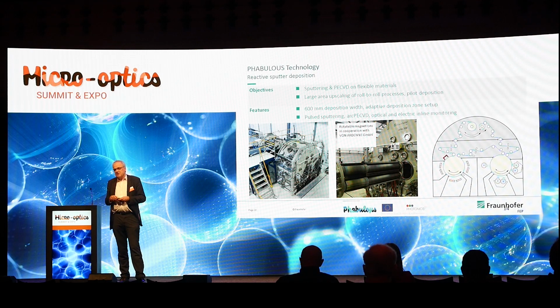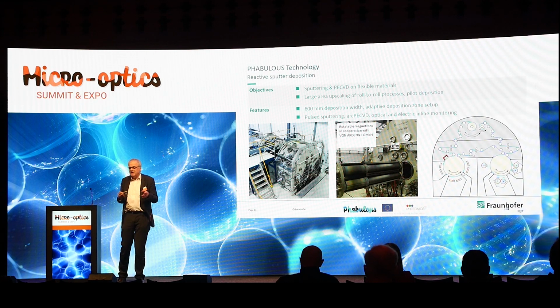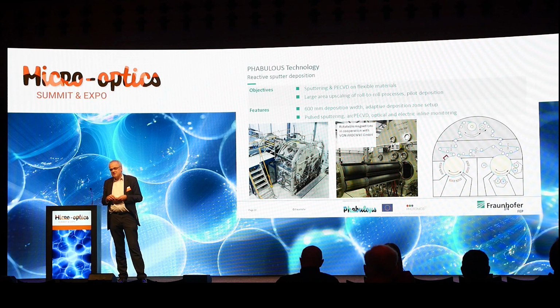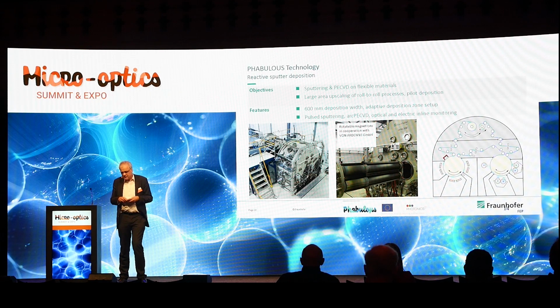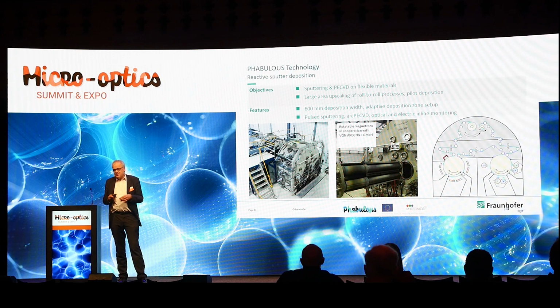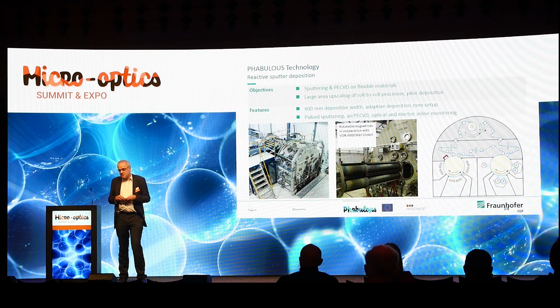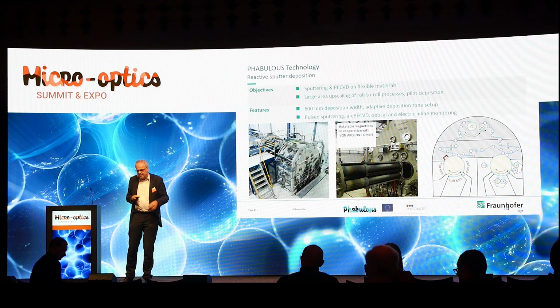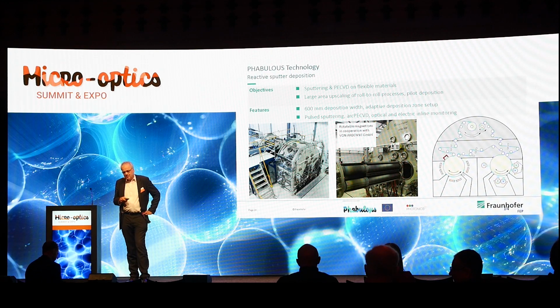It passes 2 chilling drums, and around the circumference of this chilling drum there are deposition stations, and the chilling drum is preventing the polymers from overheating. So we have only around about 30 Kelvin temperature increase, and with this we can deposit our layers on most of the polymers, also on very common ones like PET or PE.